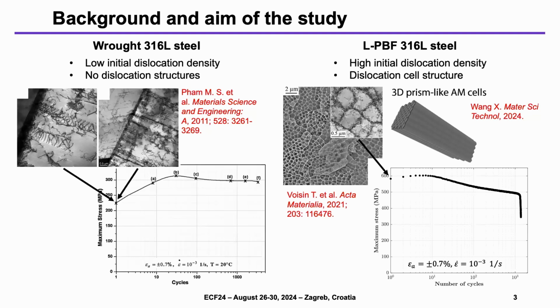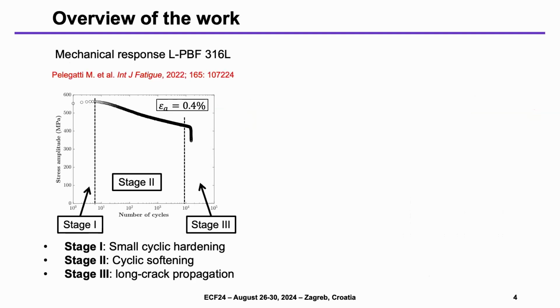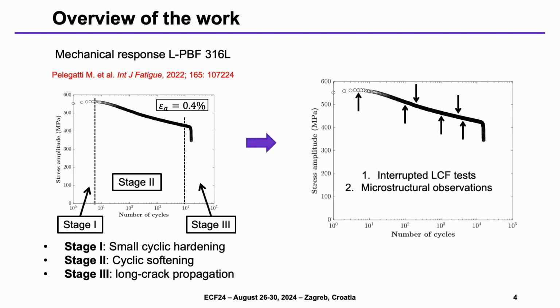So for this reason, we decided to investigate the role of persistent slip bands and persistent slip marks, even in the case of the additively manufactured materials. In this work, we decided to focus on a relatively small strain amplitude of 0.4%. Here I reported the cyclic stress response of the material, which consists of 3 stages. In this work, we decided to focus on the first part of the second stage, which is the cyclic softening. So basically, we performed some low cycle fatigue tests, which were interrupted at different numbers of cycles. And then we performed some microstructural observations on the surface and also on the interior of the material.